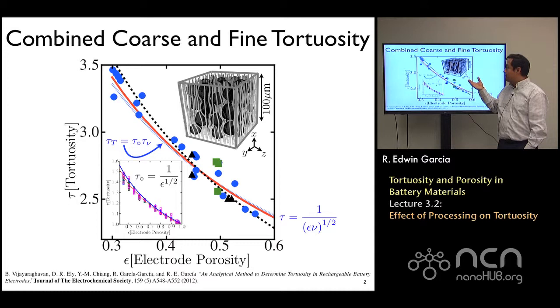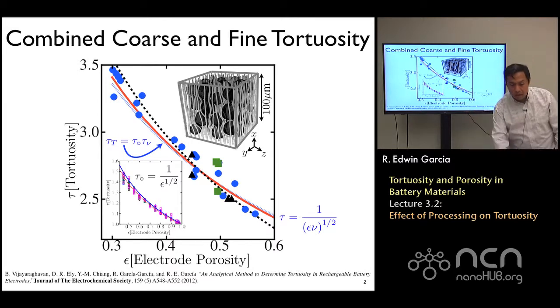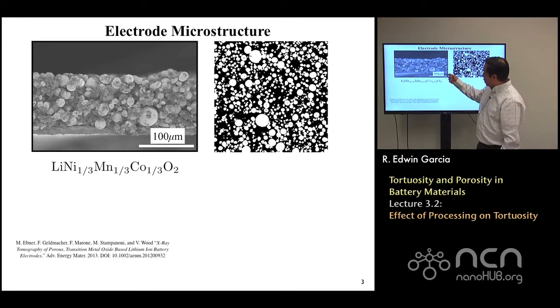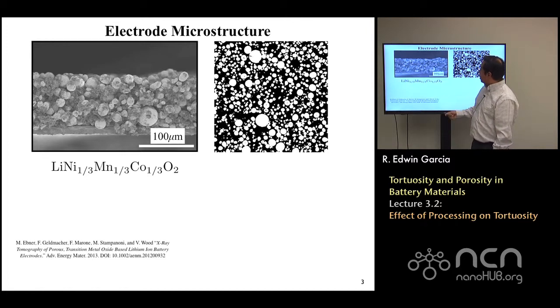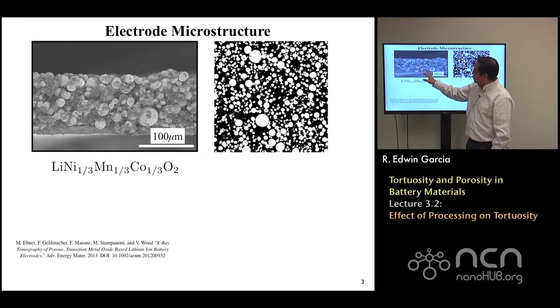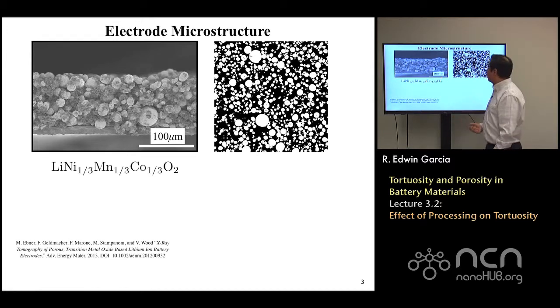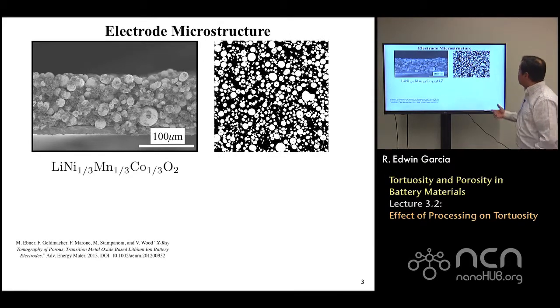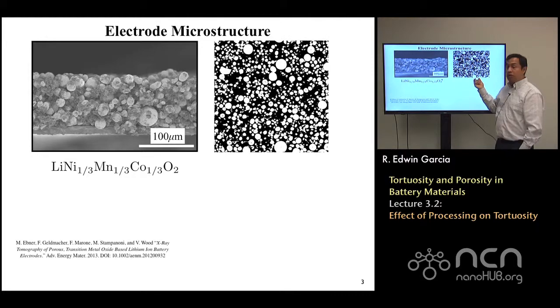This was done using just plain theory, using computer generated data. Now we can compare that directly to what you would see in a real battery electrode. These are some experiments as they were published by Vanessa Wood and Martin Ebner just last year, 2013, in Advanced Energy Materials. You can see here this micrograph showing these beautiful particles and this fluffy-like matrix, which is really the binder. And you can see here the binarized cross-section, and how the particles are very spherical for this particular structure.